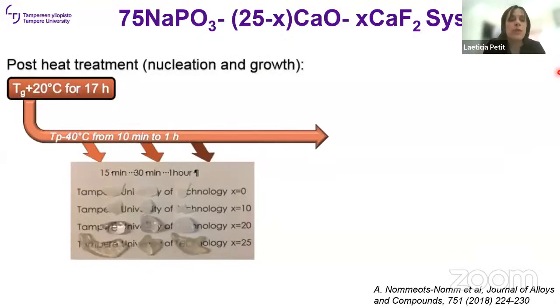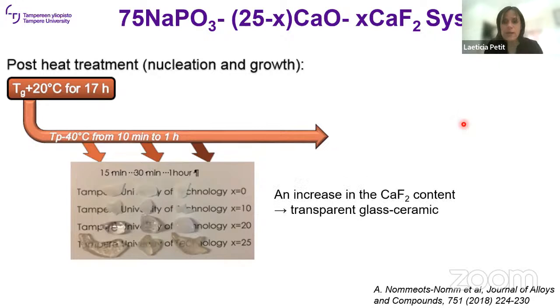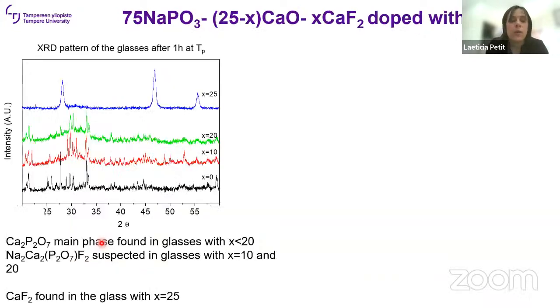So we did the heat treatment of the glasses using again this two-step process, and here you have the picture of the glasses after heat treatment. So from no calcium fluoride to only calcium fluoride, no calcium oxide. And you can see that the glasses look completely different after crystallization. They are opaque, and then they become more transparent glass ceramic. So we used the XRD to try to identify the crystal.